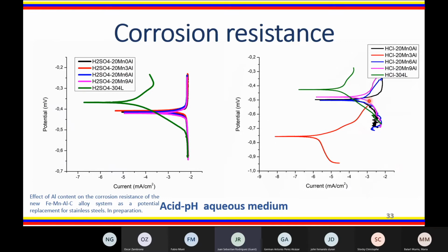Leaving aside mechanical properties, we also proposed to study the corrosion resistance of FeMnAlC steel. For this case, we only did a study on 20% manganese alloys. According to the state of the art, increasing manganese decreases the resistance to corrosion. To evaluate the resistance to corrosion, we studied an acidic medium, a neutral medium, and an alkaline medium. In this figure, the Tafel curves for sulfuric acid are represented, in which we observed that in general the behavior of FeMnAlC steels in this medium for any aluminum content is the same. When comparing with stainless steel, it is observed that there is a great difference in corrosion density and potential. It is clear that the behavior of stainless steel is much better than FeMnAlC steel.